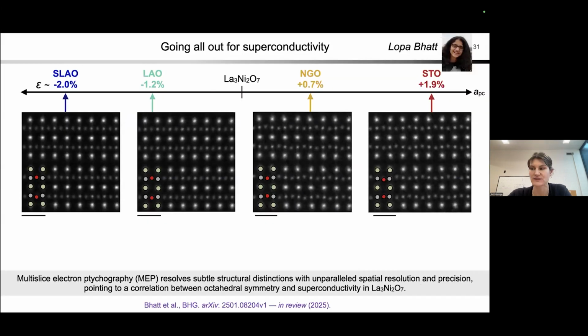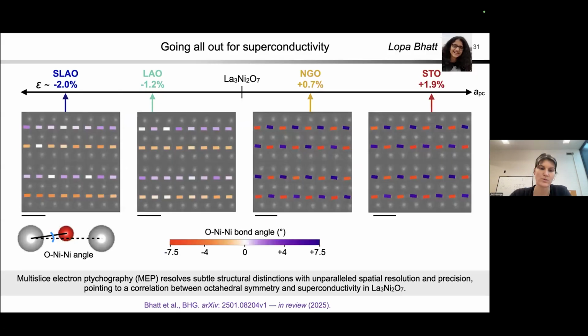And so what Lopa has been able to do is these ptychographic reconstructions across that whole strain series, where again you can see the beautiful resolution that we have, but this really opens up a lot of quantitative analysis. For instance, one thing you can look at is these nickel-oxygen bond angles. You can immediately see a difference between the samples on the left, where all of the bonds are pointing in the same direction, in this case all pointing away from that central plane, and the ones on the right, which are under the tensile strain, where you have this alternating bond distortion. This was something that hadn't been characterized before, has not been seen before. So this is really the first insight into this strain-dependent symmetry that we see in these two different crystals.